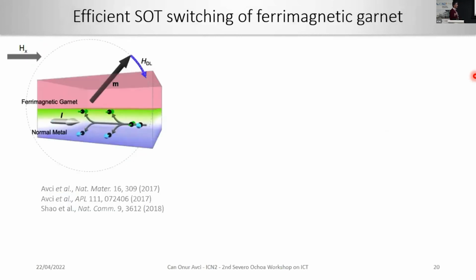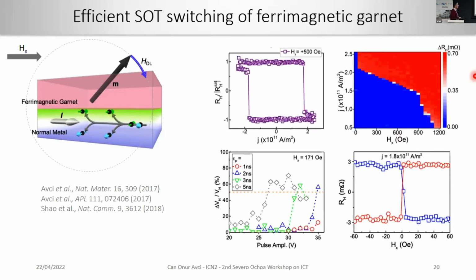And now, okay, spin-orbit torques. Since the spin current from the spin Hall effect travels in the orthogonal direction to the charge current, it can also penetrate into this magnetic material even though it's an insulator, and it can lead to magnetization switching. Here you can see that, for instance, in the presence of an in-plane field, which is required to break the rotational symmetry of the switching torque or the damping-like torque, you need a small bias field. And while using this bias field, you can switch the magnetization between up and down state in a reproducible way by just changing the current density that is going through the platinum.